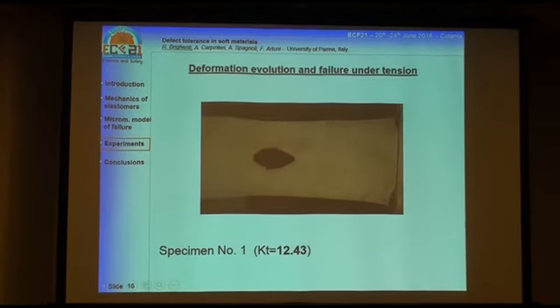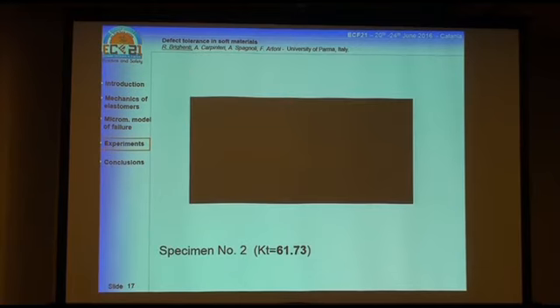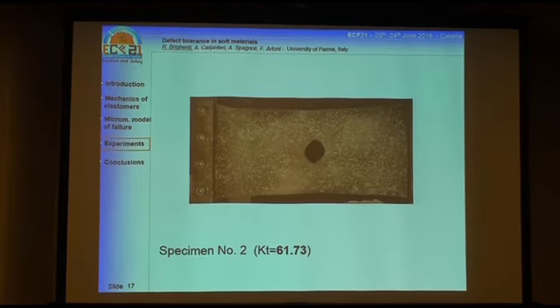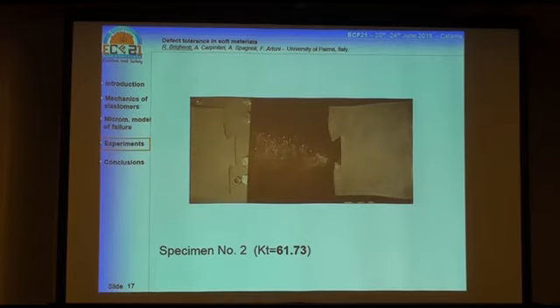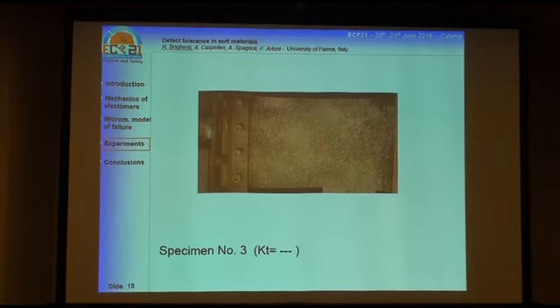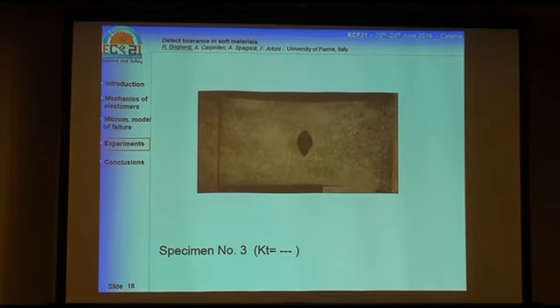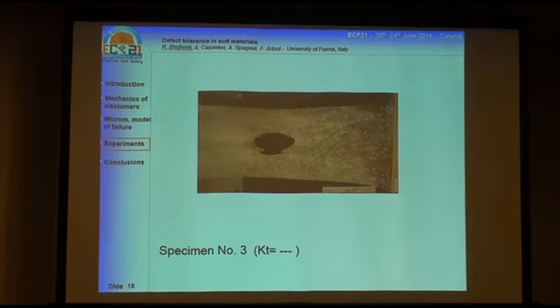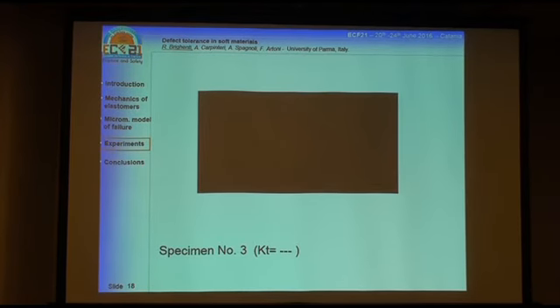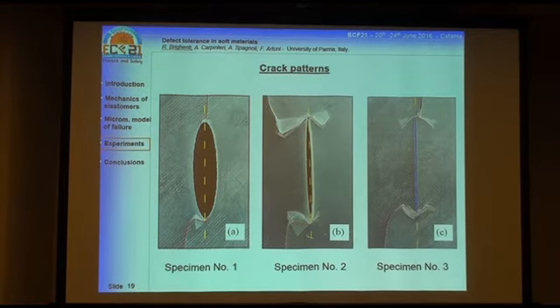Of course, this is an accelerated movie of what is happening. The test took about 20 minutes. This is the second test for the mild notch, and the last one is for the straight crack. And we have a behavior which is more or less similar to the previous ones. So we have here the crack pattern that we obtained for the different specimens. We reach almost the same final strain at the failure.